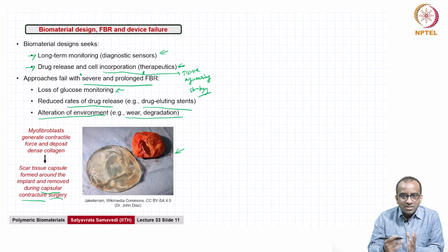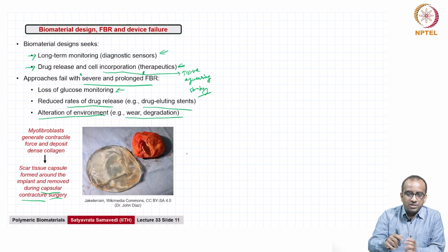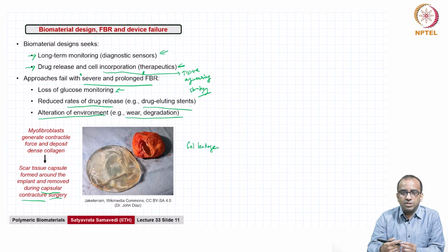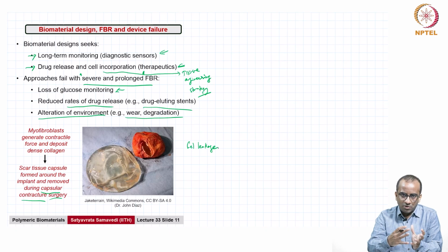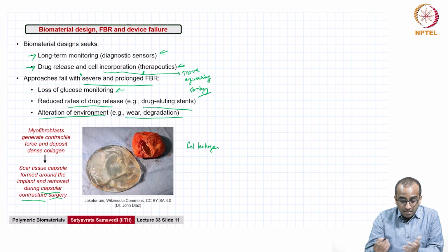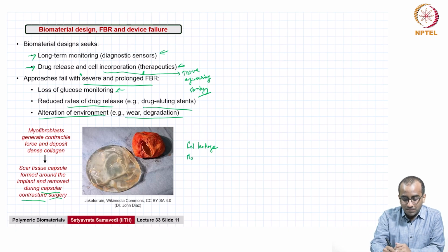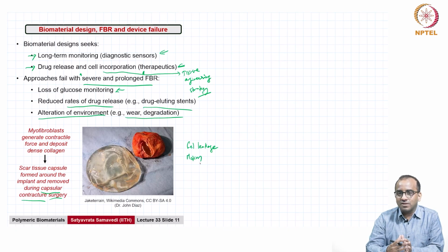Now, there are multiple reasons why this occurs with these kinds of implants. One postulated reason is potentially small amounts of gel leakage, silicone leaching out in small amounts from the implant. As we saw on the previous slide, right? If you have small silicone amounts releasing, you can have a lot of foreign body giant cell activity around those. Motion, right? Movement of the implant, that itself causes a lot of irritation.